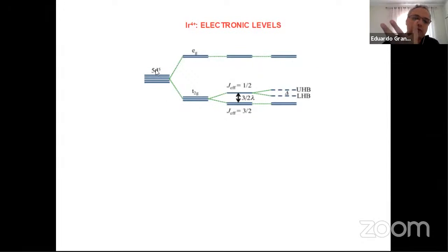If you have a free ion, you have just all these levels, but then in a solid, you have the electric fields generated by the neighboring atoms, which are oxygen. And we are interested in an octahedral environment. So this 5d level splits into the t2g level and the eg level. The t2g is threefold orbitally degenerate, and the eg is twofold orbitally degenerate, because of the electric field.